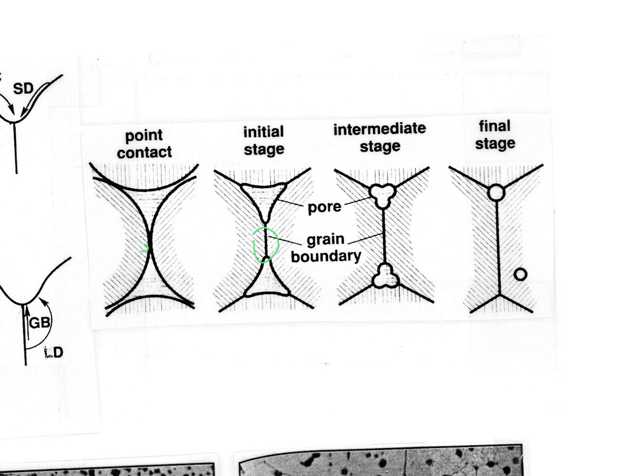And then the thing that is the macro scale here is that all this is going on. What happens to the system in terms of the connectivity of these pores? And so we know that initially all these spheres are surrounded by empty space, and we form a grain boundary, but we still have this empty space. And that empty space consists of tunnels that go all the way to the surface. All right? And so the beauty of that is, as this thing starts shrinking, as this distance finally decreases, then the air, or atmosphere, whatever it may be, turns into our enemy at this point. And so we're trying to get this air out, because the air is what sits inside those pores.